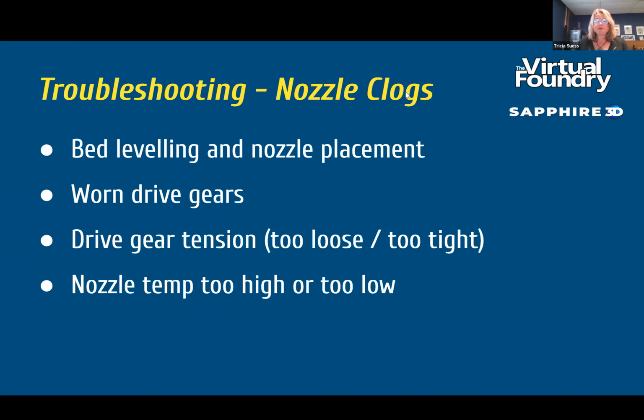So you're going to keep your printing temp between 205 and 235 C. There's a little bit of a margin of error because sometimes the nozzle isn't exactly the same temperature as what your slicer program is saying, or even what your printer is saying. But keep that nozzle temperature within that range of 205 to 235. And this is something we've experienced repeatedly: the actual temperatures on the 3D printers vary much more widely than you would expect. It's pretty common for them to be off by 10 and 15 degrees Celsius. It's fairly remarkable.